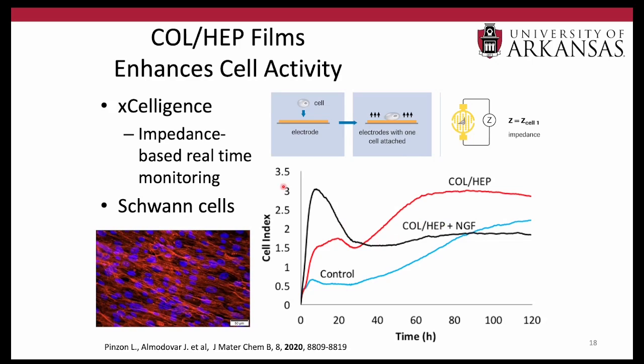So really what this data tells us is that our coatings are perhaps improving that initial cell attachment. In a sense, they're also improving the response to the NGF, which, along with the coatings, may also significantly improve cell attachment. And of course, the more cells that are attached, the more cells we have at the end of the day. In the context of nerve regeneration, that's important because these Schwann cells are really important for nerve repair. So the more that you get in that area, the better.